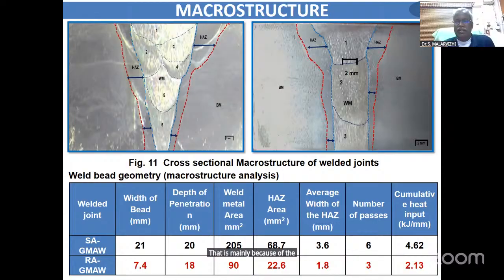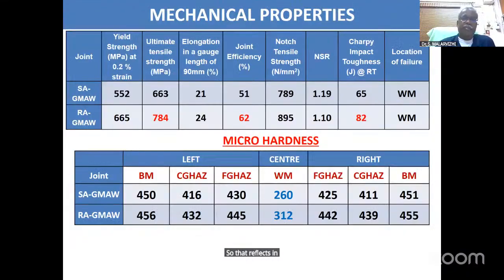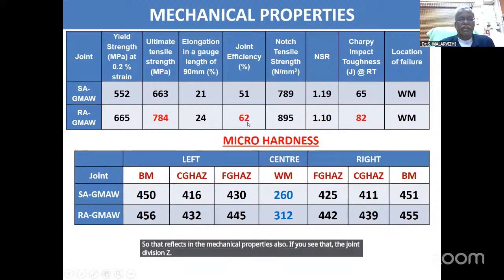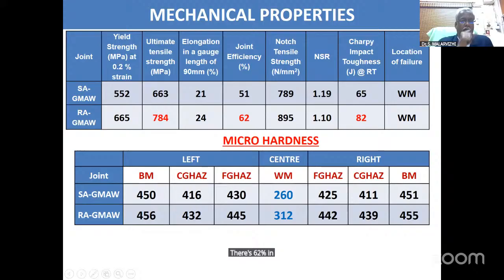That is mainly because of the cumulative heat input. Six passes lead to 4.6 kilojoules per mm, while 3 passes require only 2.13 kilojoules per mm. So the total cumulative heat supplied to the material is greatly reduced in this process. That reflects in the mechanical properties also. You can see the joint efficiency is 62% in the RA-GMAW process, but in the conventional GMAW it is only 51%.